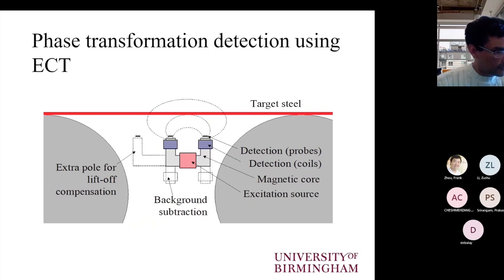Of course, eddy current testing can be used for detection of phase transformation, as I said earlier, and that is quite interesting because we can actually detect phase transformation in steel in environments where it is very difficult to extrapolate this information by different means, for example, pyrometers. So the idea is to detect the permeability variations that arise when we are below the Curie temperature.